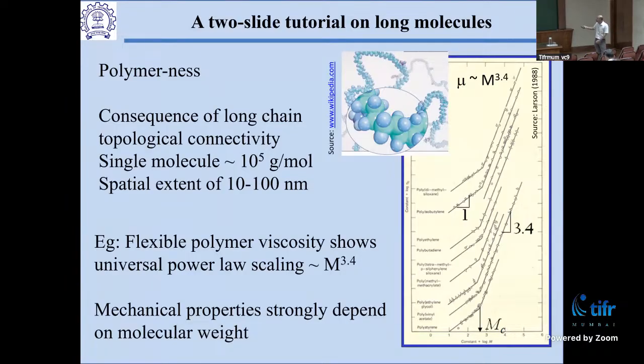So at the point at which they entangle, the viscosity, so if you don't entangle, what is the viscosity? Viscosity is effectively a measure of the time scale for stress relaxation. If I take the polymer chain and it's like a small molecule, it wiggles and relaxes stress. But if I go beyond entanglement, I can't wiggle because I can't go through bonds. It's like Pauli exclusion. So the only way I can relax stress is to diffuse in and out of those bonds. That's a different mode of relaxation, and that's the physics that gives you this 3.4 power.